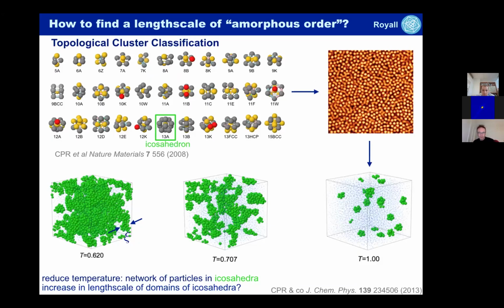To be more complete with our topological cluster classification approach, what we have is 33 different structures. They are different sizes. The letters correspond to different model materials. And it turns out that for every model material we've looked at, there is one particular structure which is the longest lived structure in the liquid. And that we call the locally favored structure. For this particular example, along the bottom of the screen, it is the icosahedron. So that's what I've indicated in green. And I show on the top right some confocal microscopy data. The bottom of the screen is computer simulation data, but we have essentially the same results from experiments as well.